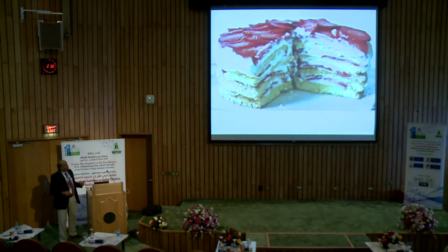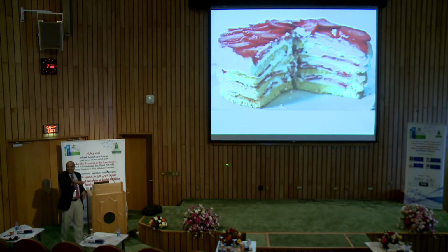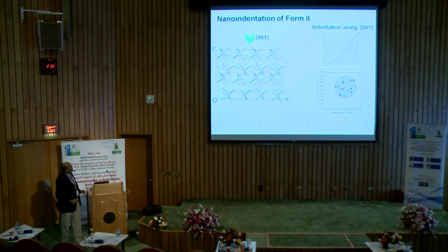So if this is like strawberry cheesecake, and you are looking, you know that it is a layered structure. There are soft layers and also relatively hard layers. If I poke from the top, I will not know that there is actually a layer structure, right? Only if I poke from the side, I will know this. All right. So first thing to do is to indent from the top.